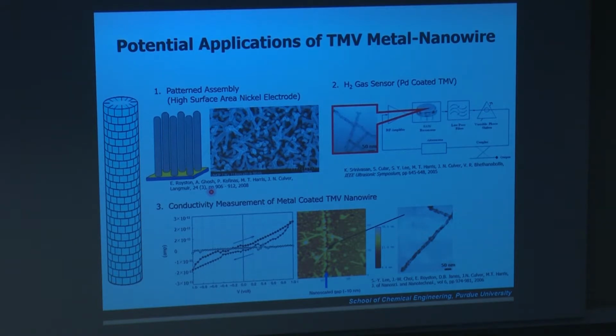TMV on a substrate, and so she was able to anchor the TMV on a gold substrate. And what happens is the TMV tends to stick straight up, and only one end of the TMV will be anchored to the substrate. And then you can coat the TMV with palladium, and after you coat it with palladium metal, you can reduce metals such as nickel and cobalt on the palladium. And one of the applications for that was in making high surface area electrodes that can be used in batteries, and what you find is that the battery has greater charging capacity with this porous surface for the electrode.